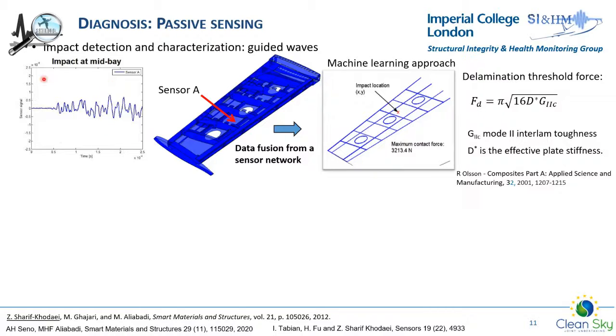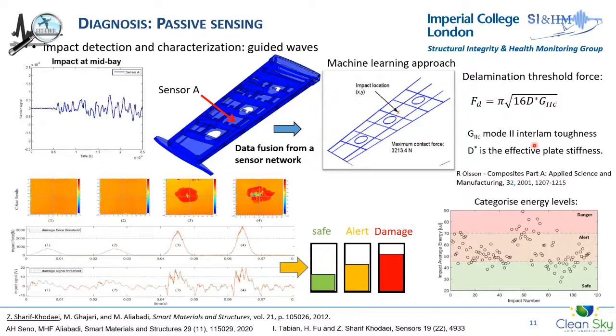The next step is post-processing. How do you extract the information from these sensor signals? A lot of work has been focused on machine learning approaches, where you take features extracted from different sensor signals, and you can then locate where the impact was based on the estimated time it takes for a wave to travel from the impact location to your sensor location. And if you have a network of sensors, by fusing this data, you can gather the location of the impact. But at the same time, more importantly, you can also say something about the maximum contact force and relate this maximum contact force to a threshold, which is the delamination threshold, and then categorize your impact based on that.